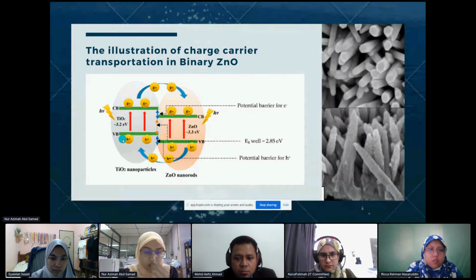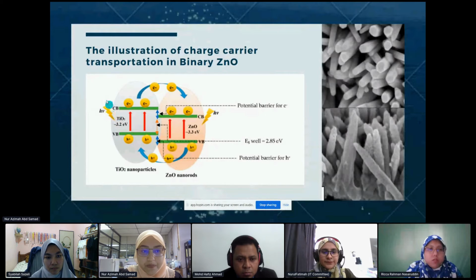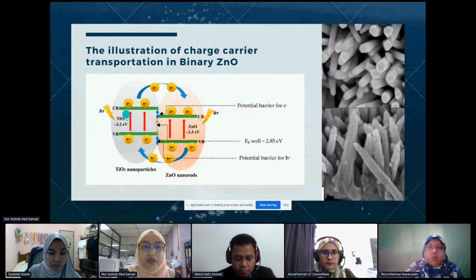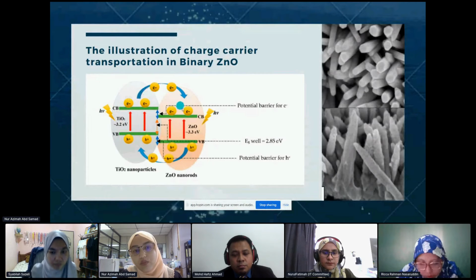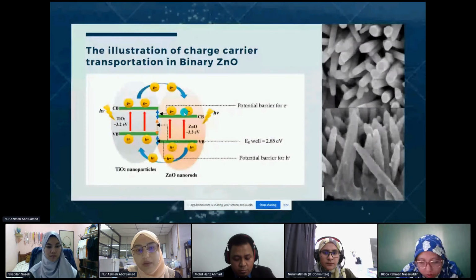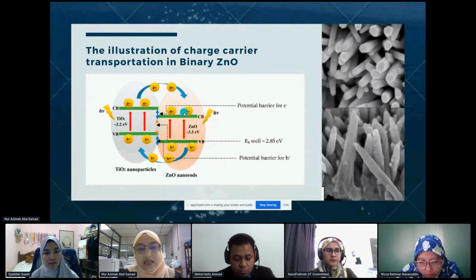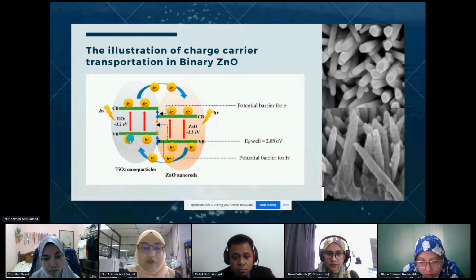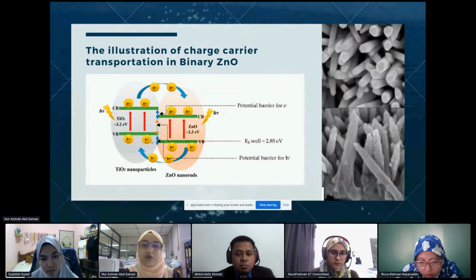For example, if the electron here jumps to the conduction band after receiving the photon, then the electron will recombine less. It moves to another conduction band, thus prolonging the movement of the electron, and it also leaves holes that will accelerate the oxidation process.